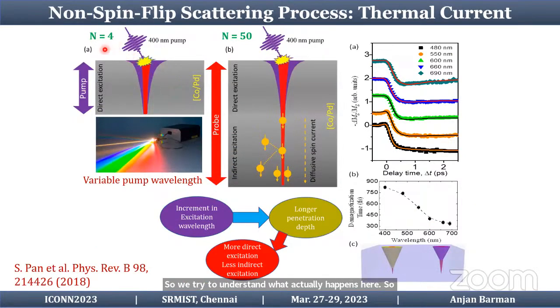In the case of a thinner sample, let's say n equals 4, the thickness is such that both the pump and probe beam can go down to the substrate, and it is the uniformly excited region which is probed. So it is direct excitation. The demagnetization that we detect is always directly excited. Whereas when you go to a thicker sample, the pump beam can reach only down to here, but the probe beam can reach way below that because the penetration depth is much higher. As a result, we have both direct excitation and indirect excitation. In the direct excitation, it is primarily spin flip scattering, whereas in the indirect excitation, it is governed by diffusive spin current or the thermal current.